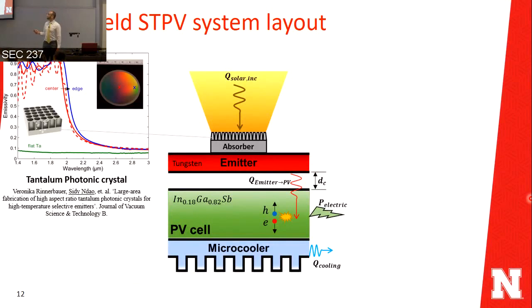The interesting thing about these photonic crystals is that they have a high emissivity at shorter wavelengths where the solar radiation happens. However, they have low emissivity where the losses happen to the atmosphere. So they maximize the absorption of the sun. We have a tungsten emitter which converts the absorbed solar radiation to near field thermal radiation absorbed by the indium gallium antimonide photovoltaic cell and creates electron holes which comprise the photocurrent. And the rest of the energy absorbed not converted to electricity is just rejected out of the system through this microcooler.